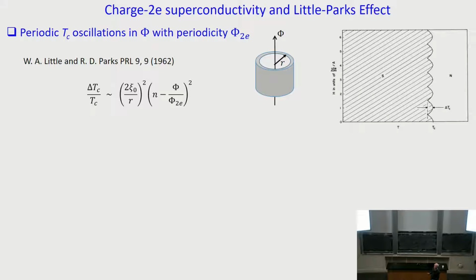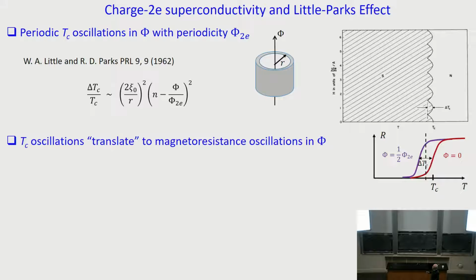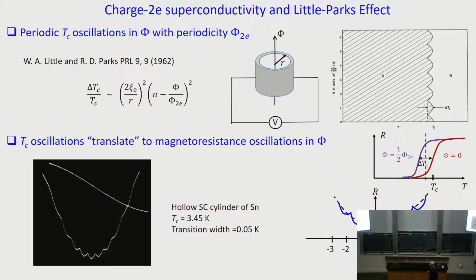And they are really creative. They said, okay, let's translate this Tc oscillation into magnetoresistance oscillation. That is very easily measured. Right? So that is like this. No flux is this. Tc is high. Maximum half flux quantum, it shifts this way. So if you're looking at one temperature, the resistivity is oscillating. So put on leads, look at resistivity. It oscillates, and it has to oscillate with this periodicity. And that's indeed what they found in tin.